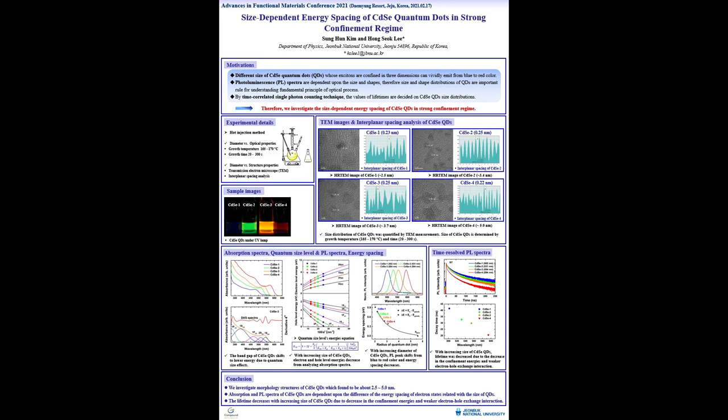In summary of this work, we investigated morphology and structures of colloidal cadmium selenide quantum dots, which were found to be about 2.5 to 5.0 nanometers. Absorption and PL spectra of cadmium selenide quantum dots are dependent upon the difference of the energy spacing of electron states, which correlates with the size of quantum dots. Thank you for your time and attention.